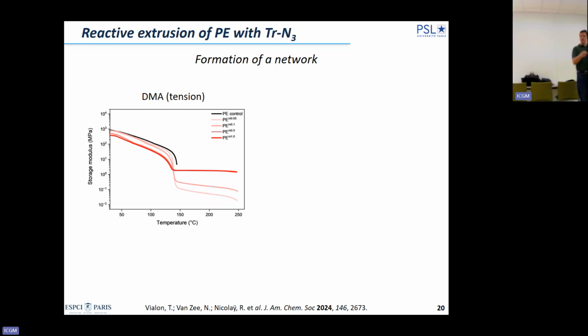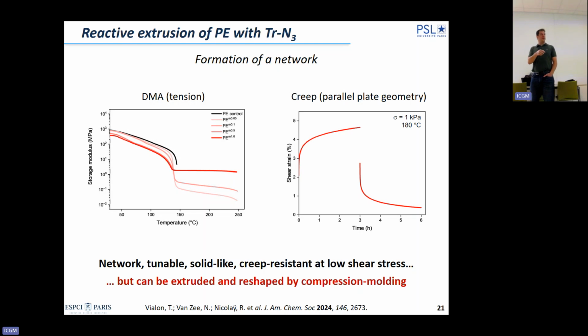So this is by DMA, and I will just repeat. We do it by reactive processing, reactive extrusion. So this is something that can be extruded, and in fact, it can be compression molded, and it can even be injection molded after. Yet, if we perform a creep experiment at 180 degrees Celsius, and we apply a moderate